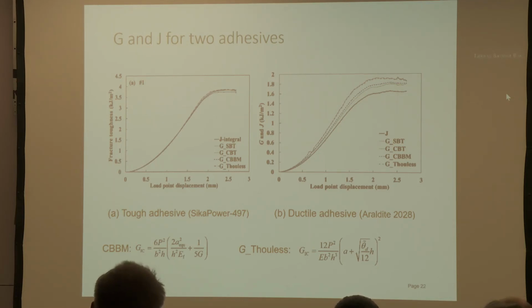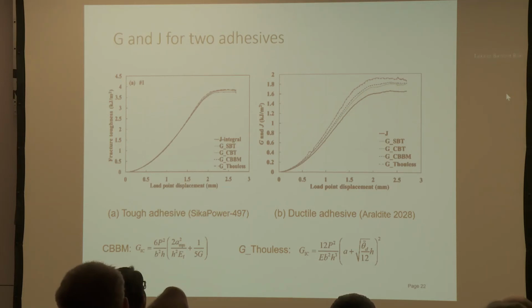However, for the more ductile adhesives, you can see this is where you begin to have differences, and it begins to be more challenging for LEFM methods, even with the corrected beam theory and the effective crack length approach to give the agreement with the J values.